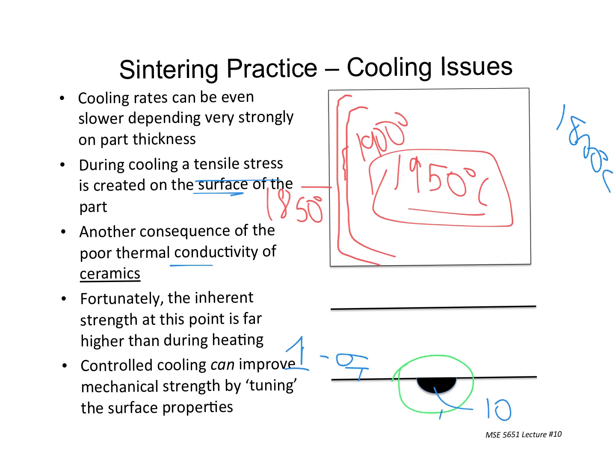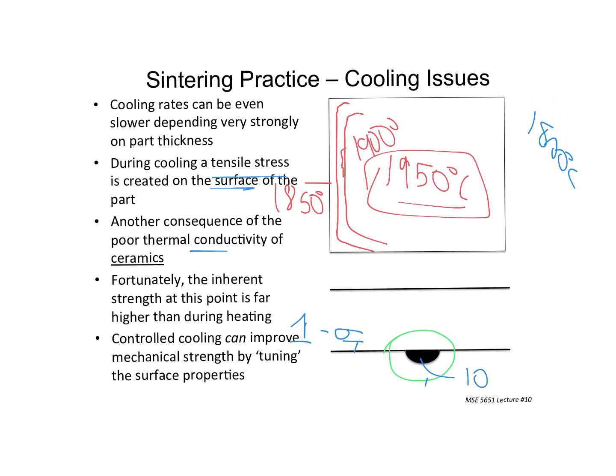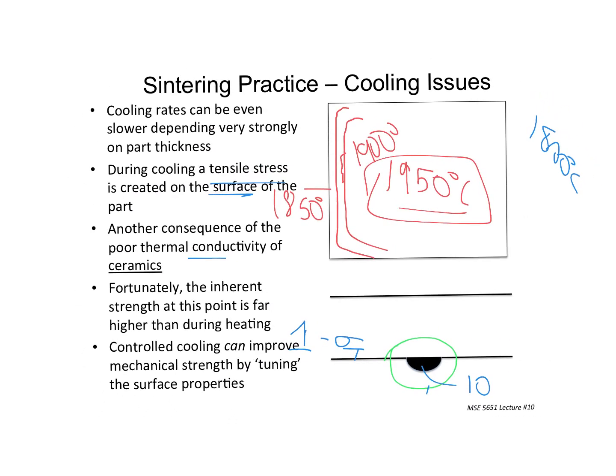So you can slowly cool it down, and then you hear a crack inside the furnace, which means that your part has self-shattered during the cooling process. So you can't go too fast in these systems, no matter what your boss says. You can go slower and end up with product as opposed to not having product. Everybody get that? The tensile stress development should make sense when you think about it. The surface is shrinking. It has to shrink because it's cooling off, and the interior is not because it isn't cooling off. And that causes these problems.